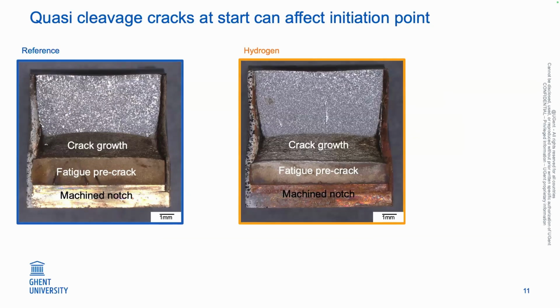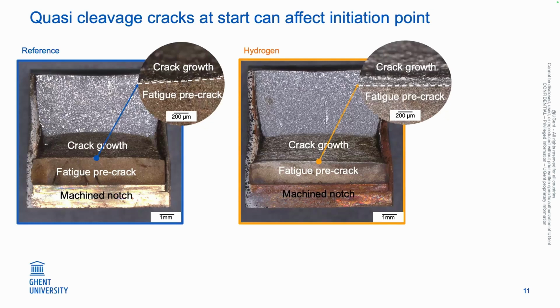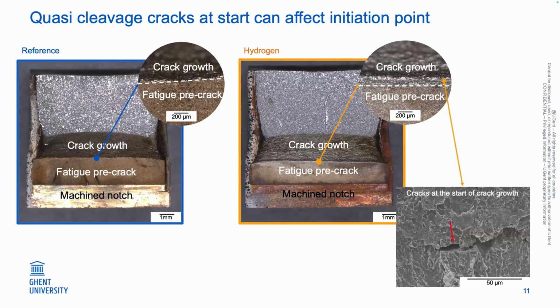Then looking at the fracture surfaces, of course, the main focus is the crack growth, to see what's the difference if we include hydrogen in our specimen. If we zoom in on the start of our specimen, we see a shiny band on the pre-charged hydrogen specimens. We go deeper into that band with SEM, and we see quasi-cleavage and small cracks. This behavior can already explain why we have a lower toughness at the initiation point.